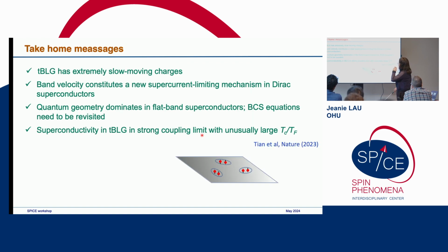Okay, so let me just summarize this part. Twisted bilayer graphene can have extremely slow-moving charges, a flat band. So in theory, the Fermi velocity can go to 0 if you hit exactly the magic angle. So there's a new current limiting mechanism, which is different from conventional superconductors, and quantum geometry dominates the contribution. So the BCS equation will need to be revisited in this case.